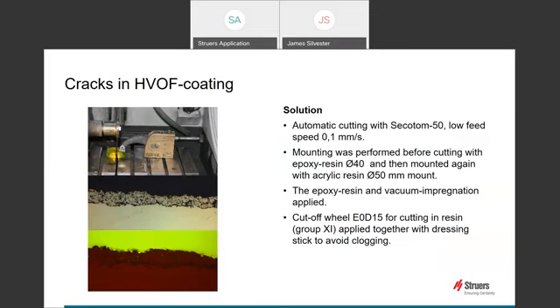A trial was carried out where the sample was mounted in an epoxy resin prior to cutting. This mounting had two benefits. We could use vacuum impregnation, which would show us if there had been any damage prior to any preparation, and also support the coating during cutting, making it more likely to resist fracture. In the images on screen, we added EPO dye to the resin, which gave us an excellent contrast between the coating and the resin. If any cracking had been present before cutting, the vacuum impregnation would have pulled this resin into the gap left by the crack and proved a pre-existing crack of the coating.